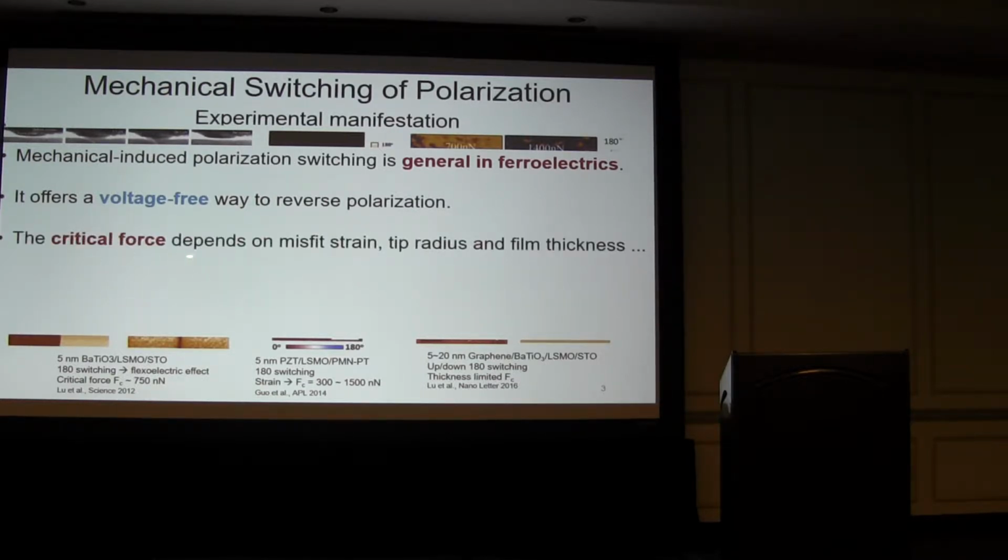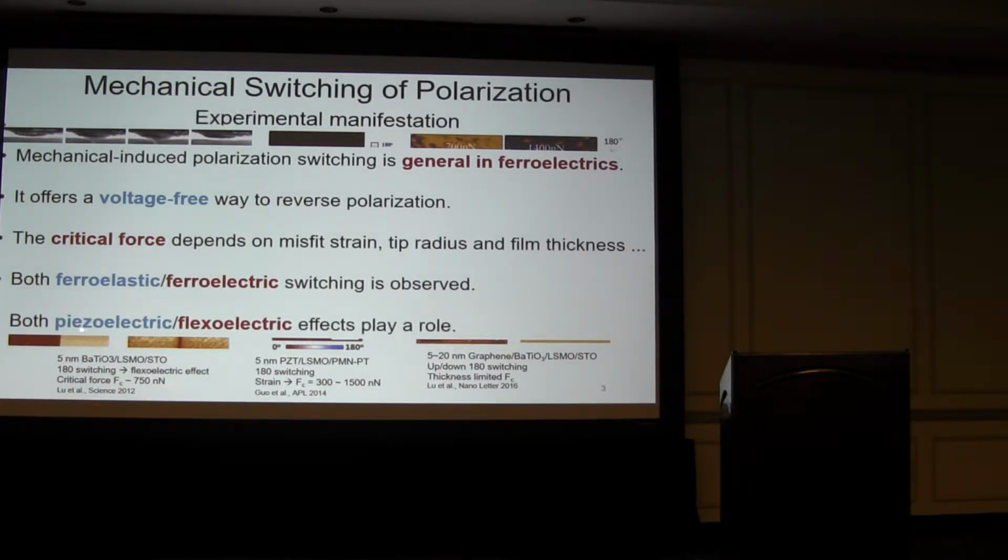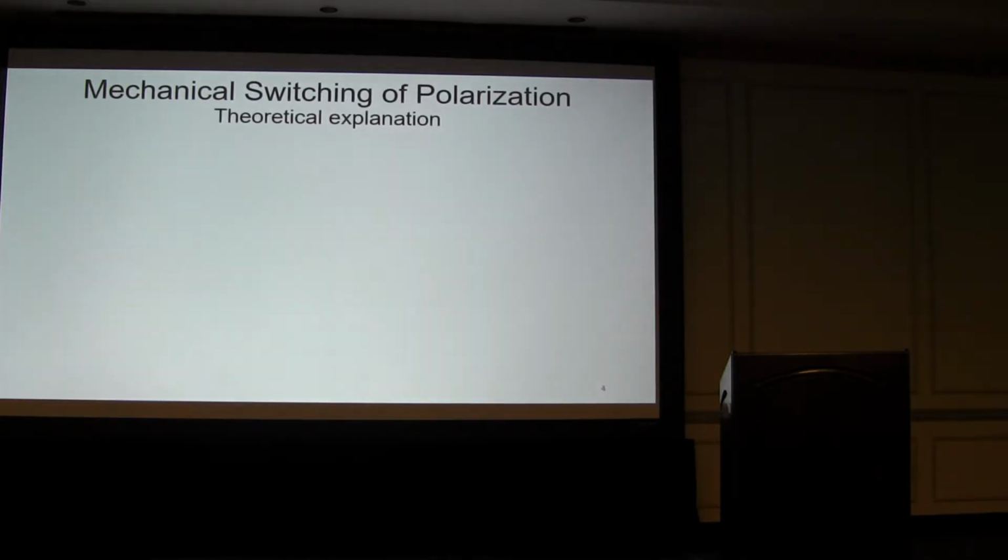And also the critical force for achieving this switching depends on the misfit strain, tip radius, film thickness, and other factors. In all these cases, both ferroelastic and ferroelectric switching are involved. This is related to the piezoelectric and flexoelectric effects at the same time. And from a theoretical perspective, this phenomenon has been studied by our group with phase field modeling.